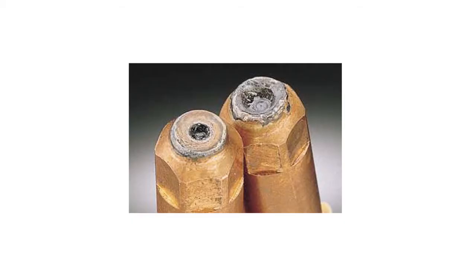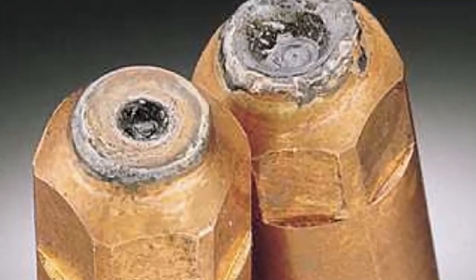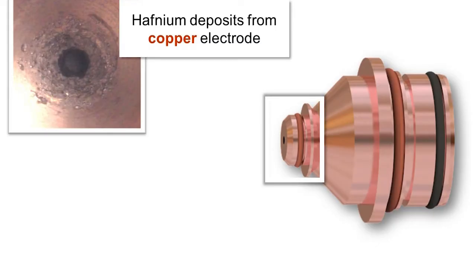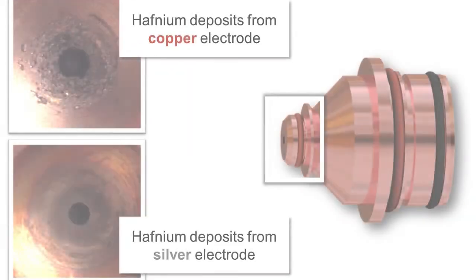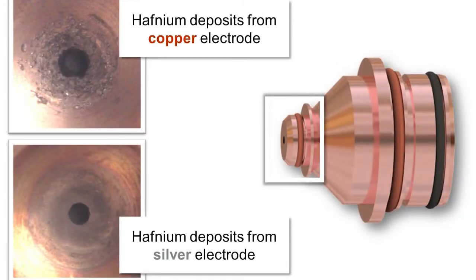At the end of life of a copper electrode, pictured here, copper and hafnium are expelled from the electrode and deposited on the inside wall of the nozzle. When this happens, the plasma arc may jump from the plate to this material inside the nozzle, cutting away the nozzle and often the shield. In silver electrodes, pictured here, the stronger bond between silver and hafnium and better thermal conductivity of silver results in less material deposited on the inside nozzle wall, extending the nozzle life.